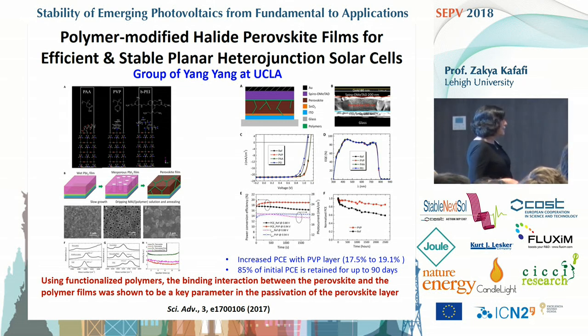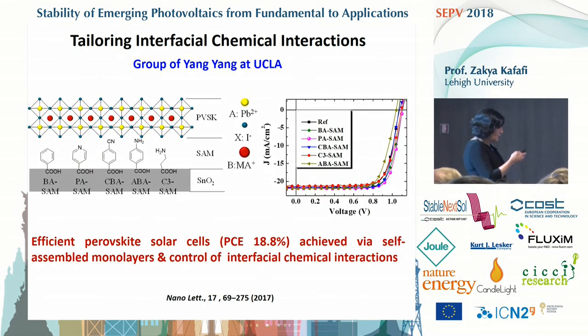And he was able to increase the power conversion efficiency, for instance, with one of the polymers, PVP, from 17.5% to 19%. He succeeded in doing that while 85% of the initial power conversion efficiency was retained for up to 90 days. So that's what he tested. He also published another study where he was able to achieve efficient perovskite solar cells via self-assembled monolayers, and again, controlling the interfacial chemical interaction in this case.